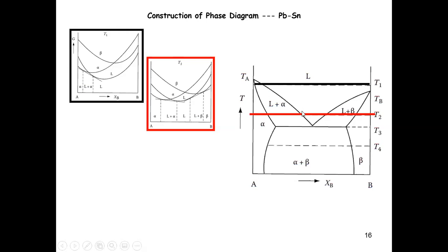This is liquid alpha liquidus. This is liquid beta liquidus, but they're all liquidus, separating the pure liquid phase from the liquid plus solid coexistence. Okay, so that's the red line. Again, it's a little bit more complicated. You have to worry about the coexistence region of two different solid phases with liquid, but it's still a binary construction for each coexistence, right?